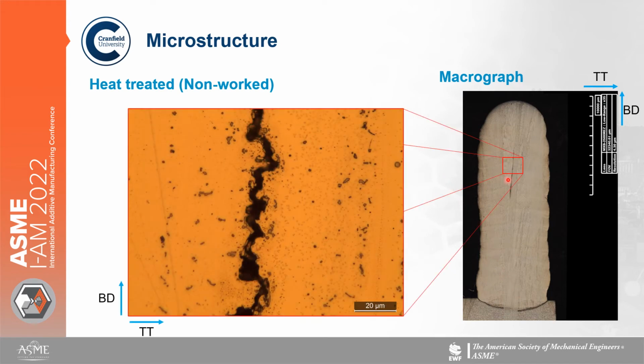And then we also have a nice crack here in the middle of the sample. And at the crack edge, you can see precipitate at the crack edge, which we'll investigate in the next few slides.